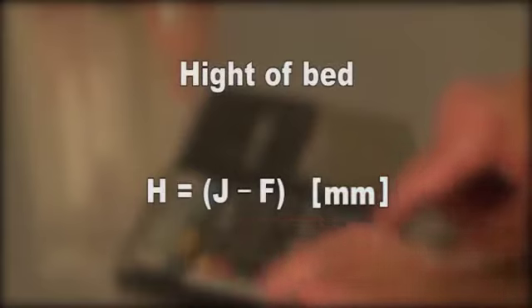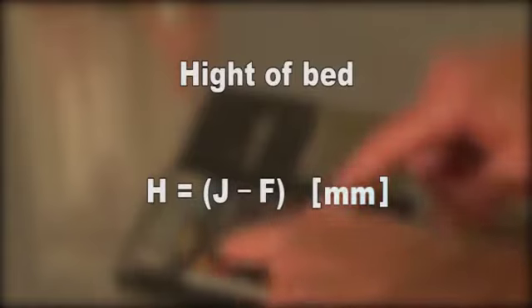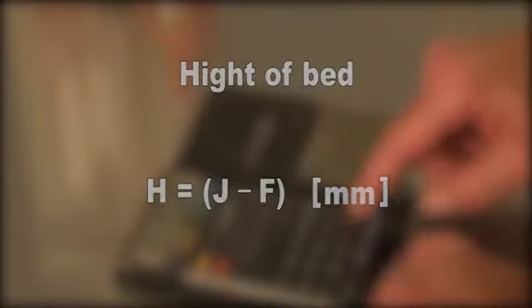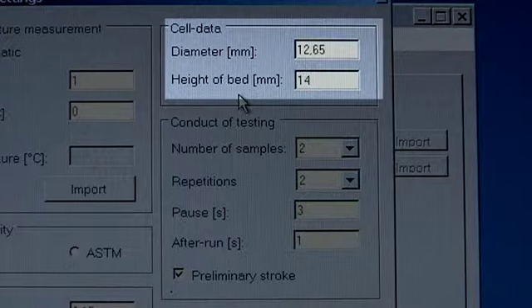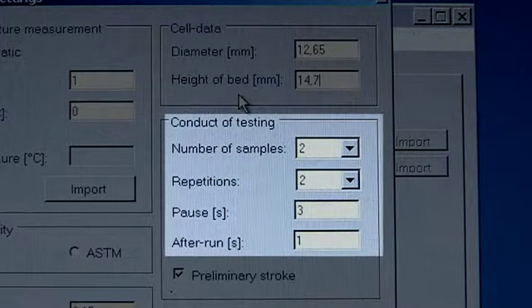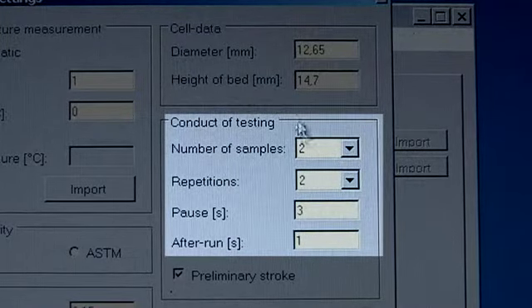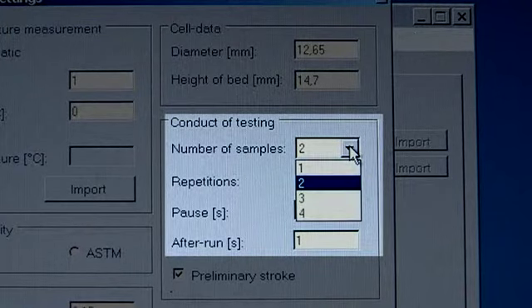Now, the powder bed height H can be mathematically determined. This is done according to the following equation. The test bed height, H, is calculated as the difference of the interior cell dimensions J minus plunger length F. The values of the cell diameter and bed height are calculated to 2 places behind the decimal point and entered into the PC field. In the execution field, enter the number of samples and number of tests performed for determining the apparatus constant. In each case, there are 2.